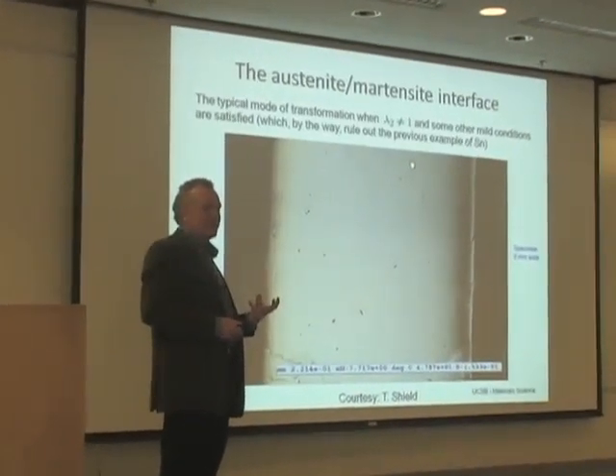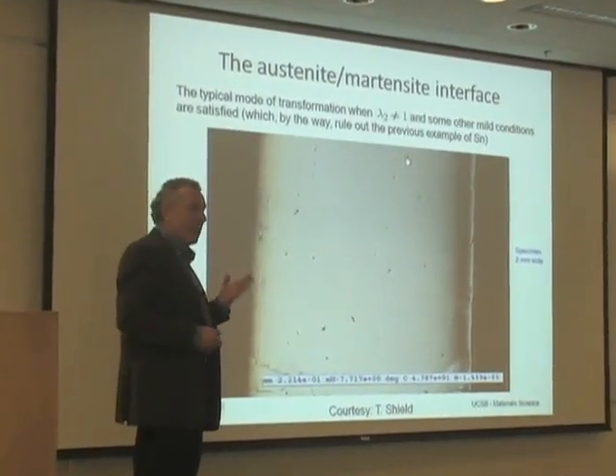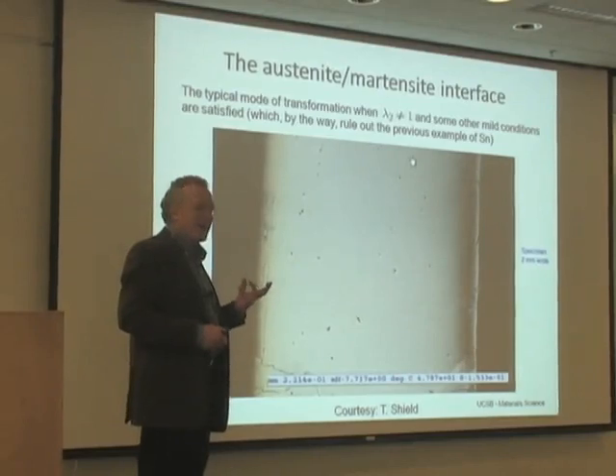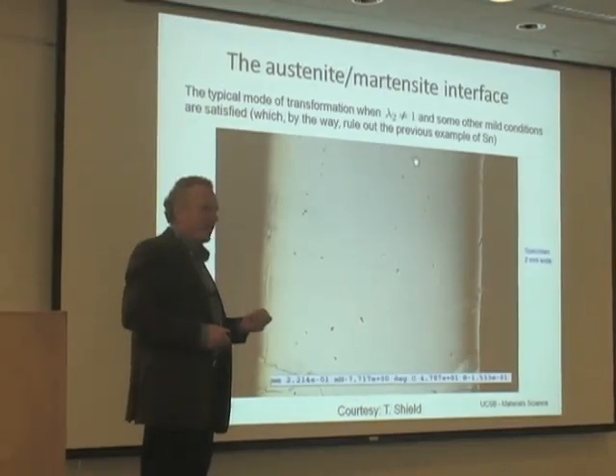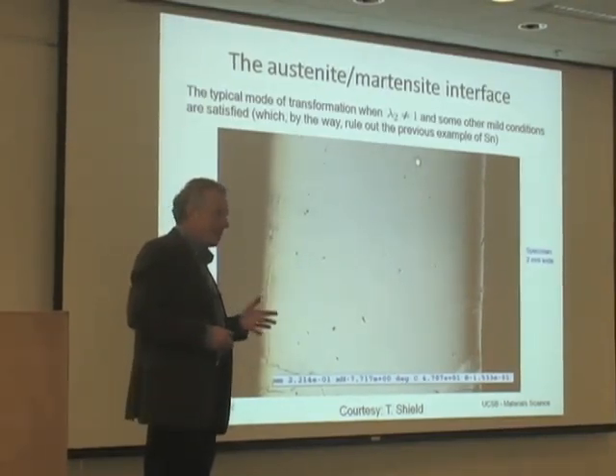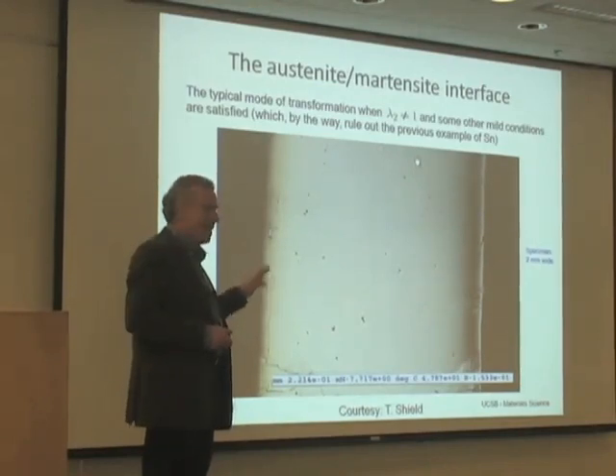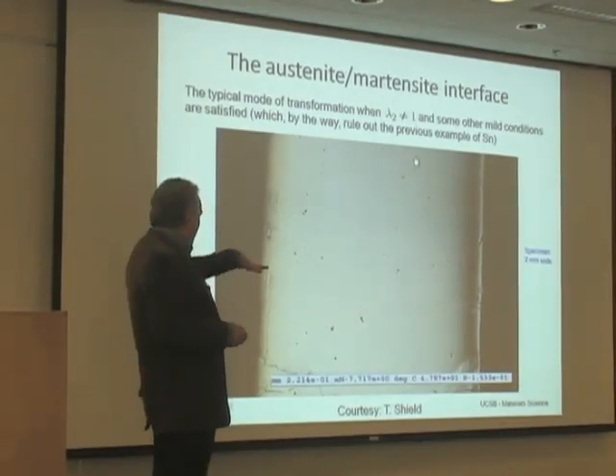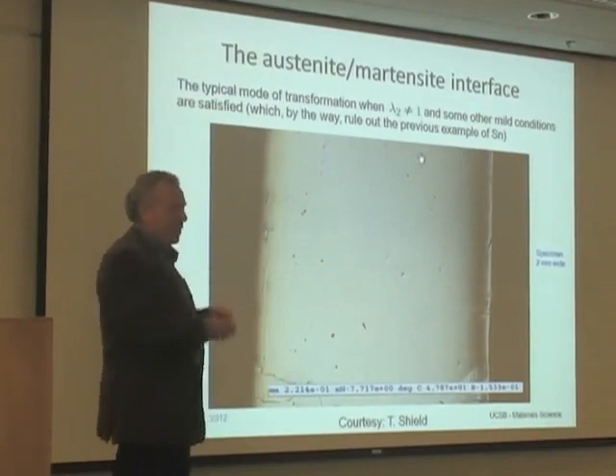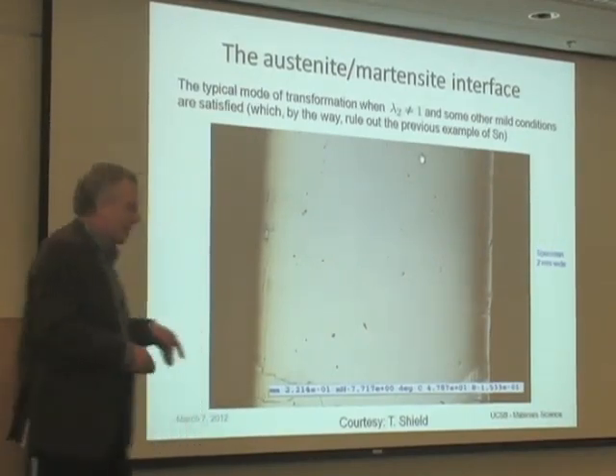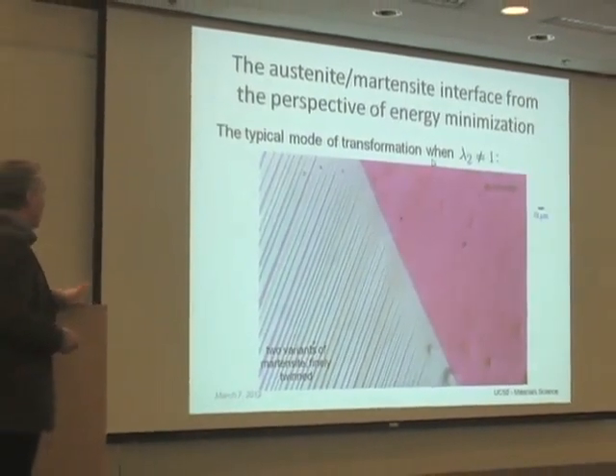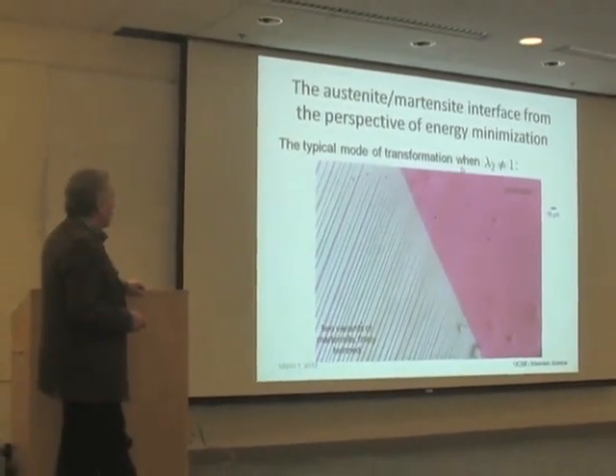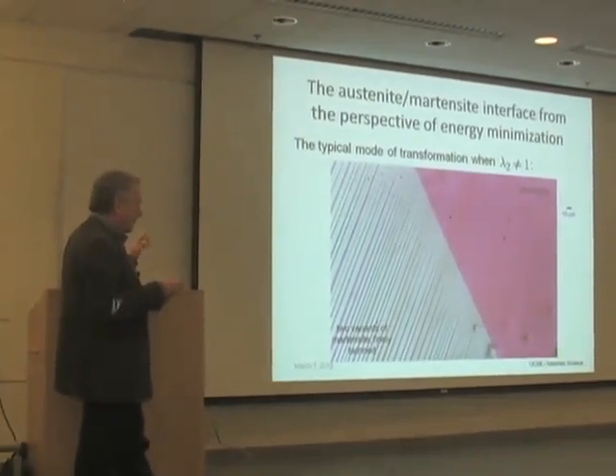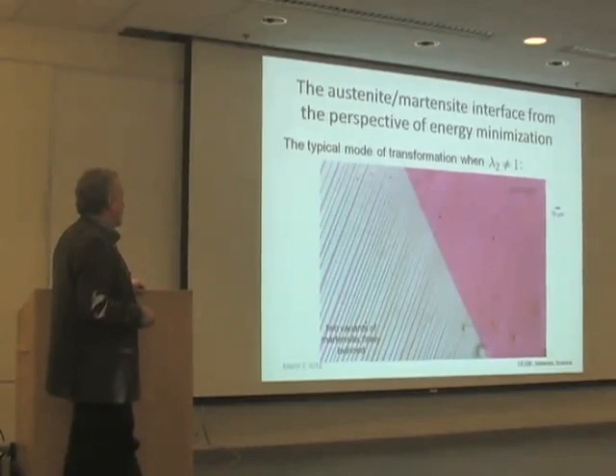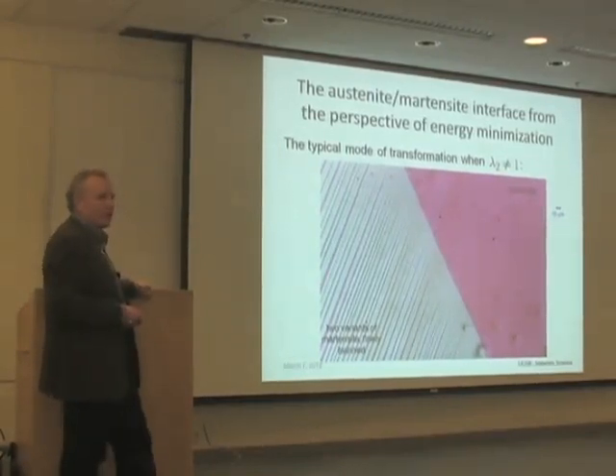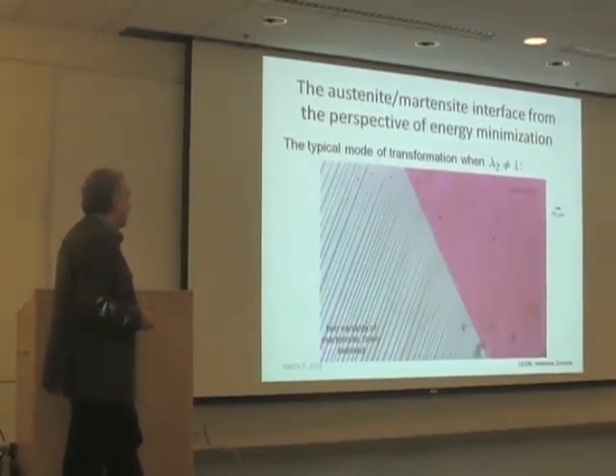So what is this coming from? It's coming from the fact that austenite and a single variant of martensite are not compatible with each other, and I'll explain that in a minute. But somehow, with this microstructure, this is the kind of low-energy pathway between those two phases. So let me show it again. And this is the typical mode of phase transformation in first-order structural phase transformations with no diffusion. It's called the austenite-martensite interface.